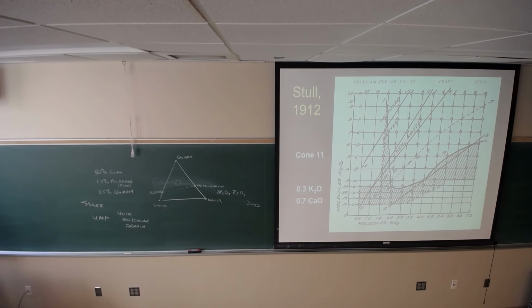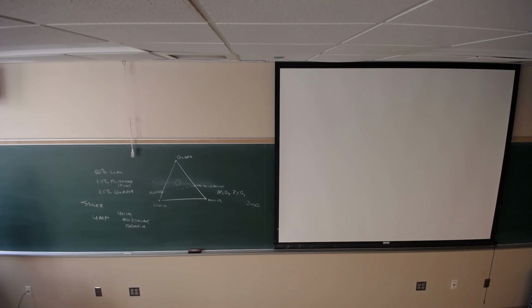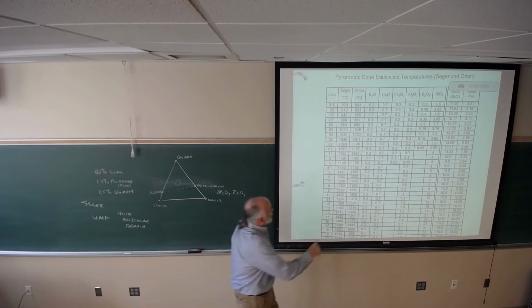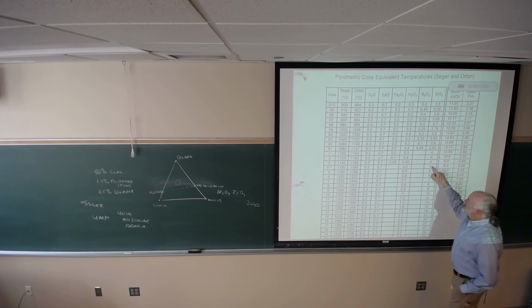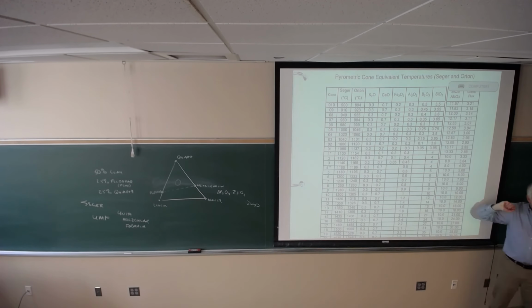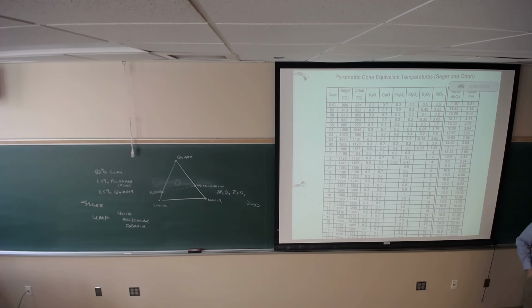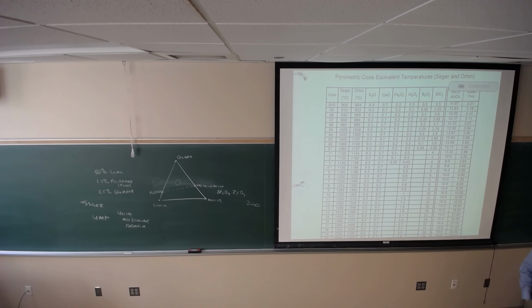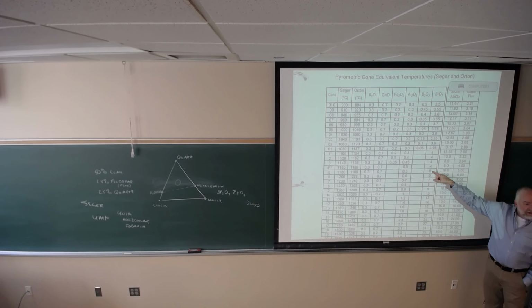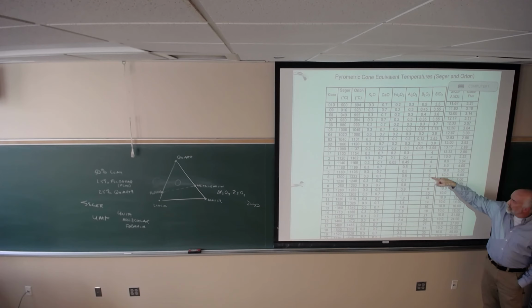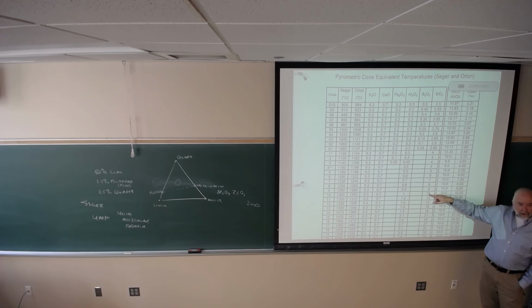Let's go back to the cone thing for a minute. We're going to talk about cones, but only a little bit more as the semester progresses. Cone 4 was first because cone 4 had 4 moles of silica. It's actually remarkably logical, right? And then cone 5, oh look, it had 5 moles of silica, and then cone 6. It even did pretty well until you got to 10, then the wheels came off the bus, but I didn't care so much about that at the moment. But this is where he started.